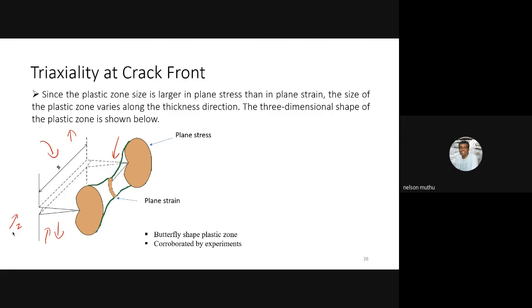But when you go inside along the thickness of the material, the tensile load tries to make it contract. But it is not allowed to contract because of the resistance offered by its neighboring materials. Therefore, there is a generation of a third principal stress, in the third direction, and that will introduce triaxiality. Triaxiality means non-zero principal stress in all directions. That triaxiality is going to result in smaller sizes of the plastic zone. If the size of the plastic zone is smaller, then the rate at which the crack will propagate is going to be relatively higher compared to the scenario where the size of the plastic zone is bigger.